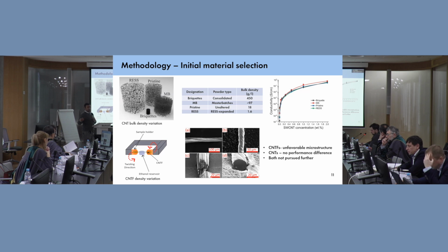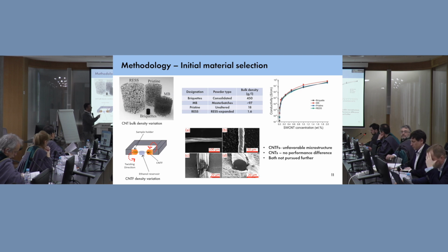And we need to make samples in different batches. We use the same materials, the same processing method. But of course, there's always going to be variance between these. And we wanted to eliminate these factors, and we went with something higher in this case. Our selection of this weight percentage was not extremely high, for extremely high conductivity where we will see less piezo-resistive response, but enough to eliminate these variances of the manufacturing near percolation.